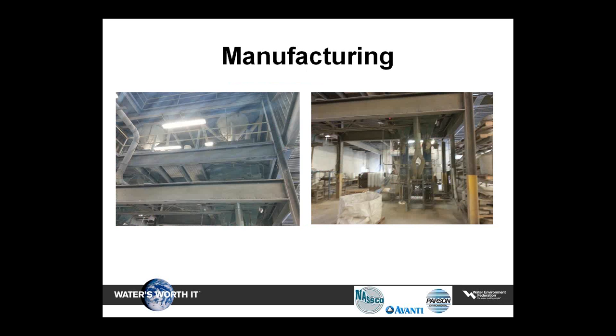Cementitious lining materials designed for manhole rehab are typically manufactured from either Portland or calcium aluminate cements. Even so, all of the products using either type of cement are designed to provide structural integrity, protection against future infiltration, and corrosion resistance of varying levels, which we will discuss later. Compressive strengths are typically 4 to 5 times greater than the existing manhole substrate, which will return the manhole to better than new condition by providing a higher level of structural integrity. They are usually fiber reinforced to aid in resisting surface cracking and require around 1 to 1.25 gallons of water per bag, with bag sizes ranging from 50 to 75 pounds.